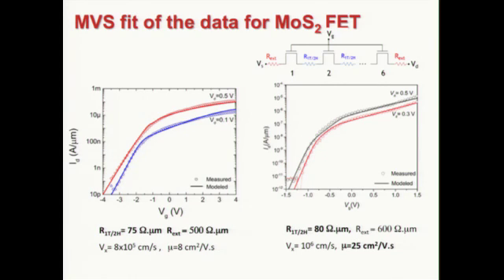It turns out that the internal resistance between these two phases is as low as 75 ohm micrometer. As I said, we have a junctionless, seamless contact, and the metallic phase has a relatively low work function, so that forms a very good ohmic contact to the semiconducting one. But of course, we still have the external contact resistance between MoS2 and metal, which is about 500 in the single layer and about 600 in the tri-layer MoS2. Velocity is more or less the same, about 10 to the 6 centimeter per second. And as expected, the exfoliated tri-layer MoS2 has a larger mobility of about 25 square centimeter per volt second compared to 8 square centimeter per volt second in the monolayer MoS2.